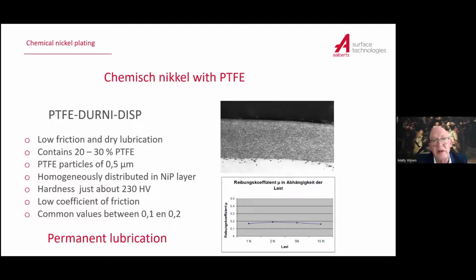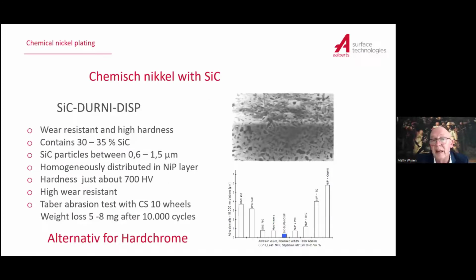Then what you can do is include PTFE in your chemical nickel layer. So you lower your coefficient of friction, and the layer contains PTFE, permanent lubrication up till the end of the layer. You can put silicon carbide into the chemical nickel layer, which gives you a more wear resistant coating that's even close to hard chromium.